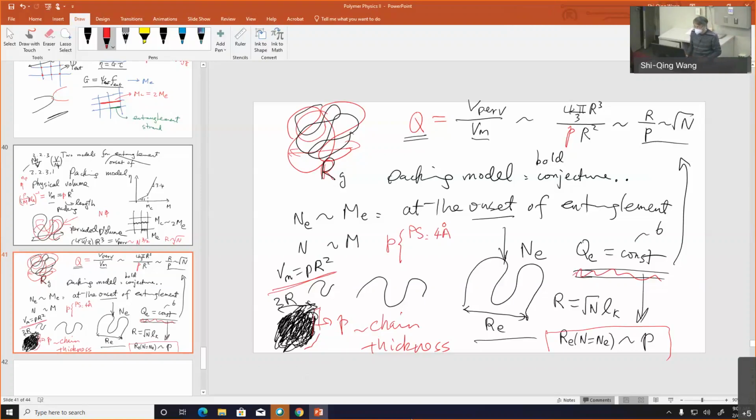Polyethylene is something on the order of 1.7 angstroms. Which, of course, is more than double. The styrene is more than double the ethylene. Which means my end-to-end distance for styrene will be twice as long, more than twice as long.